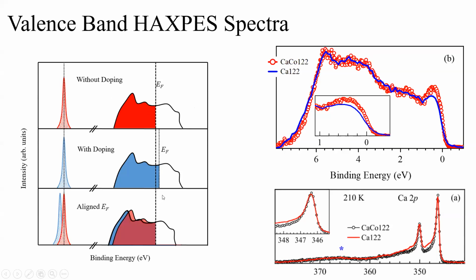And just to align the Fermi energies in these two compounds, if you compare these two spectra, you will see a small shift in the spectrum. Usually people compare the core level spectra and see whether there is a shift in the core level or not. If there is a shift, it means that you have doped electrons, and if there is no shift in the compound, it means there is no electron doping or no charge carrier doping in this compound.